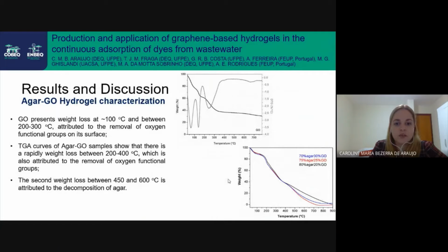We have also done the thermogravimetric analysis for graphene oxide, and also for the agar graphene oxide samples. The 3 samples produced show a rapid weight loss between 200 and 400 degrees Celsius, which is attributed to the removal of oxygen functional groups. And a second weight loss was between 450 and 600 degrees Celsius, which was attributed to the decomposition of agar.